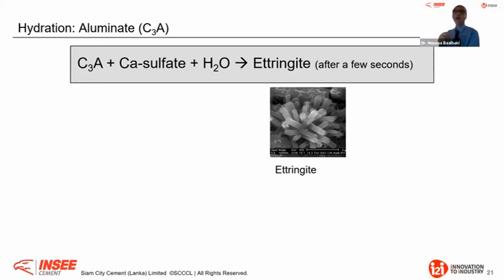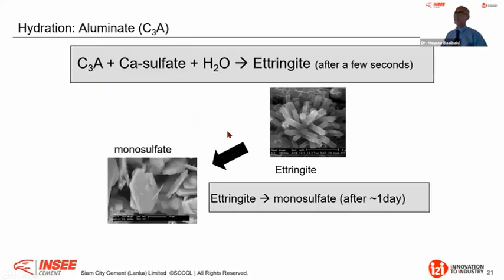This is why when you produce your own cement, you can do some optimization, which I will show you later, because it is very important to optimize this couple between C3A and calcium sulfate. And a couple of hours or days later, this tri-sulfo aluminate, ettringite, will transform to monosulfo aluminate. That will be most of the last product you find in your concrete.